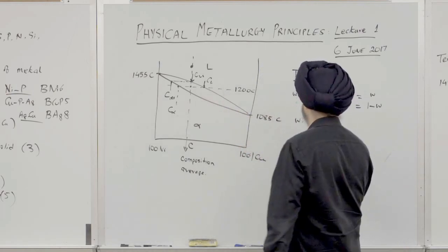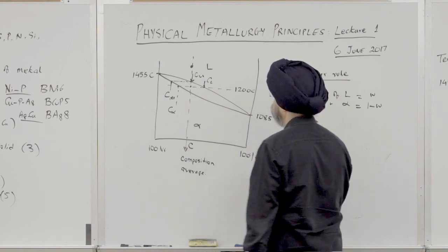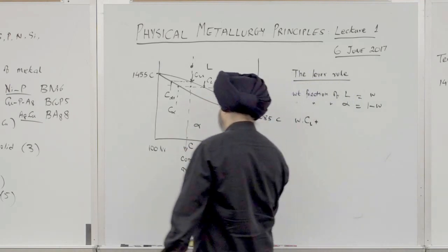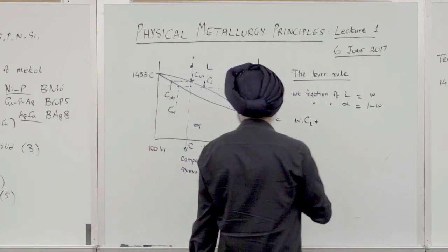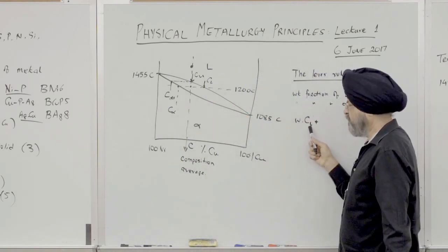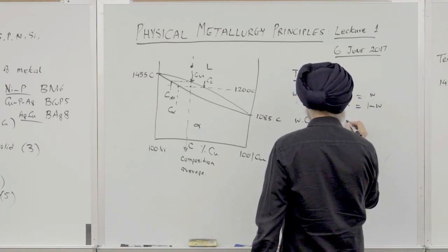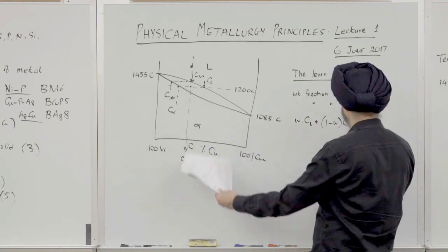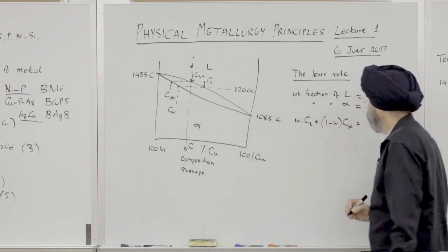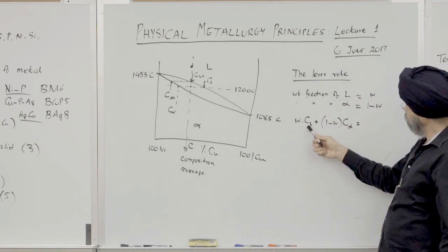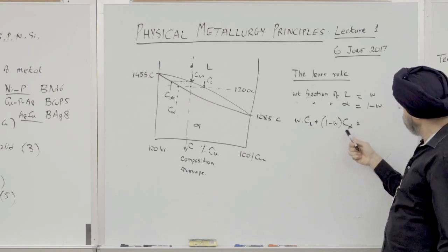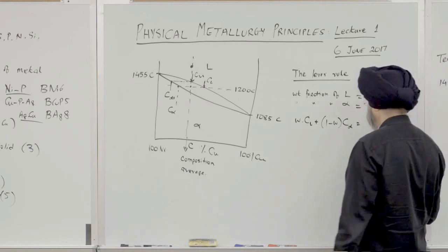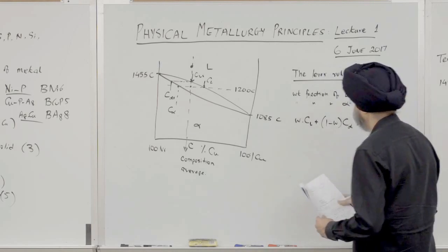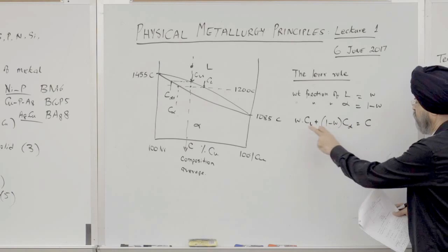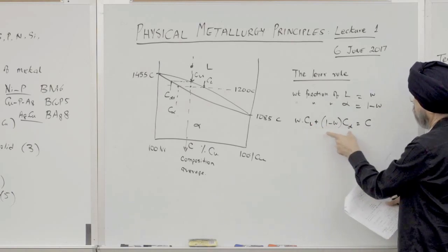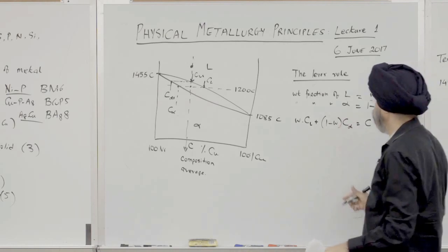times the composition of the liquid, which is Cl. When I say composition of liquid, I mean the copper content, because this axis is percent copper. So W, which is the fraction of liquid, times its copper content, plus 1 minus W times the concentration of copper in the solid, C alpha, right? So W is the amount of liquid, that's the concentration of copper in the liquid. 1 minus W is the fraction of solid, and that's the composition of copper in the solid. So that has to equal just C, right? That's the average composition. So copper in the liquid plus copper in the solid is equal to total copper, correct?